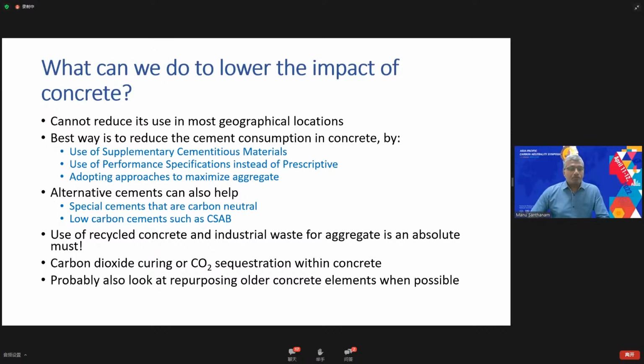One thing we cannot turn our eyes away from is the use of recycled concrete and industrial waste for aggregate, because aggregate—the part that's likely inert inside the concrete—contributes nearly 75% of the volume. So most of the concrete is basically aggregate. If you start utilizing industrial waste and recycled sources, you can reduce the impact on natural sources.